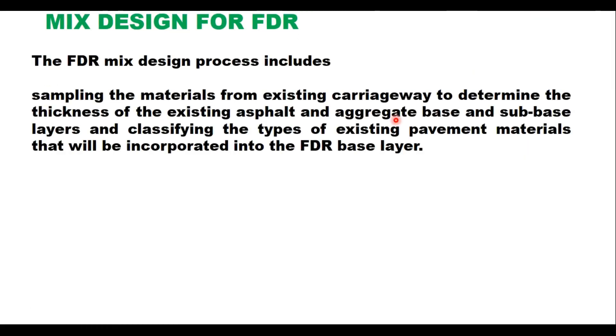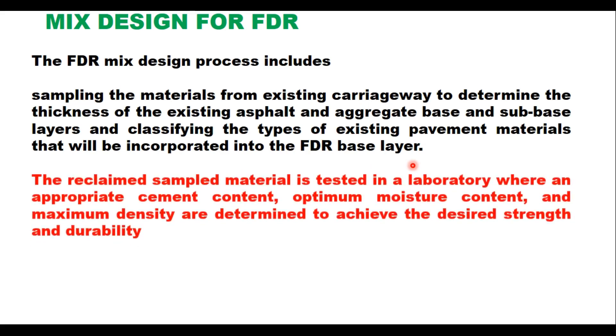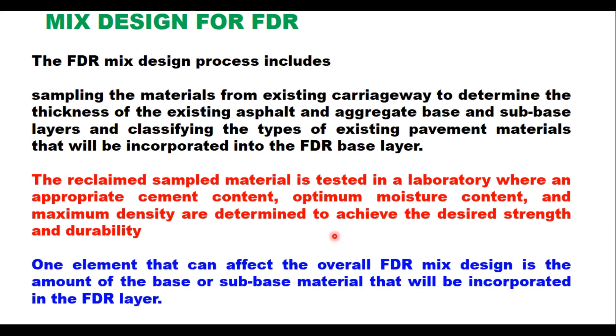One of the key steps in the full depth recycling operation is the mix design. The mix design process includes sampling material from the existing carriageway to determine the thickness of the existing asphalt and aggregate base and sub-base layers, and classifying the types of existing pavement materials to be incorporated into the FDR base layer. The reclaimed sample material is tested in the laboratory where an appropriate cement content, optimum moisture content, and maximum density are determined to achieve the desired strength and durability.